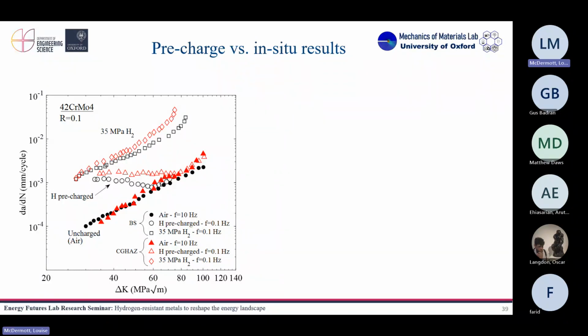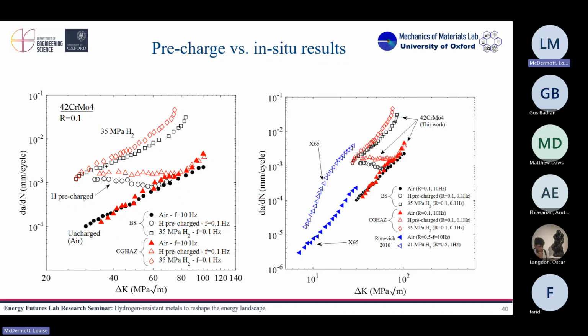And it's interesting, right? Why do we have this different behavior? So here, this is unusual. When you see this kind of propagation curve, you usually see a Paris propagation region that's more or less linear. And here we have a flat region, where the crack growth is constant. And it resembles more a stress corrosion cracking process. Okay? So we said, okay, let's compare it with the literature.